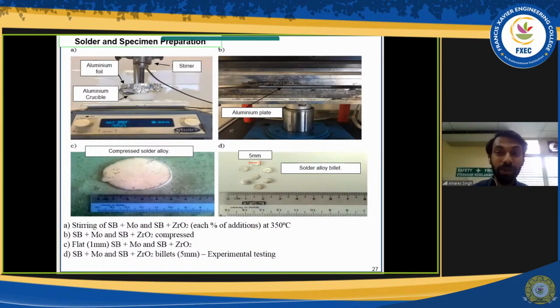Why smaller in size? Go back again, it's because of the trend towards miniaturization. I don't want to be using a high mass or high density solder. So the solder alloy will be manufactured, or punched, into billets of size 5 mm. These 5 mm billets, you can see in the descriptions below. I've mentioned SB plus MO is basically SnBi plus molybdenum nanoparticles of 1, 2, and 3% separately. Correspondingly, likewise for the zirconia addition, 5 mm will be used for the experimental testing.